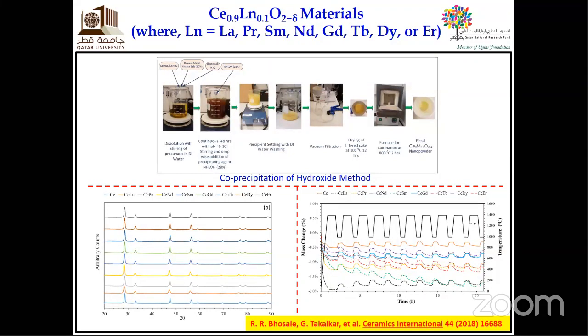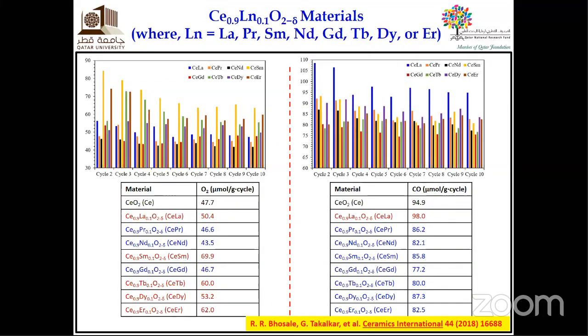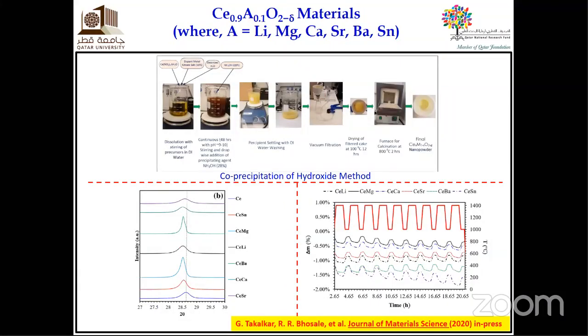Now, here the things are quite interesting. If you check the O2 production capacity, almost 5 out of 8 dopants successfully helped ceria to improve the O2 production capacity. For example, lanthanum, samarium, terbium, dysprosium, erbium actually help to improve the thermal reduction capacity of ceria. But when it comes to the CO production capacity, only lanthanum is beneficial. So based on this study, we found out that if we want to improve the O2 production capacity, we have 5 options from lanthanides. But if we want to improve the CO production capacity, we have only 1 option from lanthanides, which is helpful.